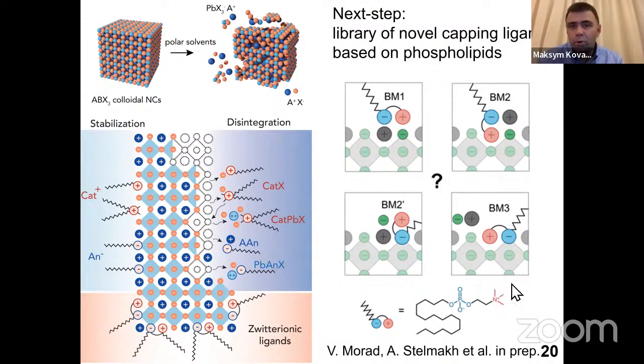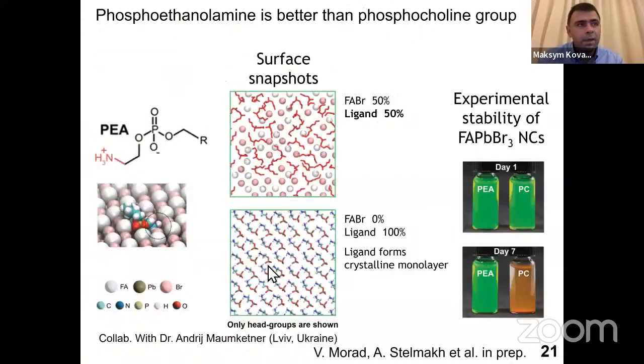But the most interesting finding was also to question whether this quaternary ammonium moiety, typical for phospholipids, is ideal or not. Because in principle, this is a permanently charged cation, and it sounds like it's a good group, but it's a little bit bulky for this site. And so we then checked, what if we take a primary ammonium group, which is 3 hydrogens instead of 3 methyl groups.